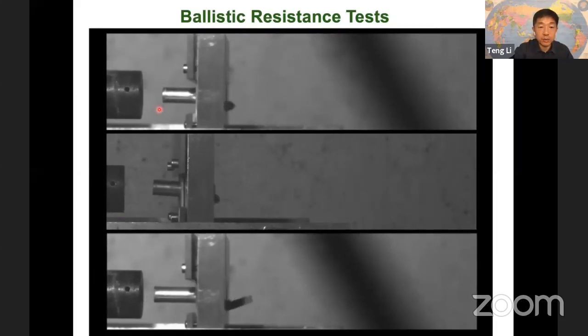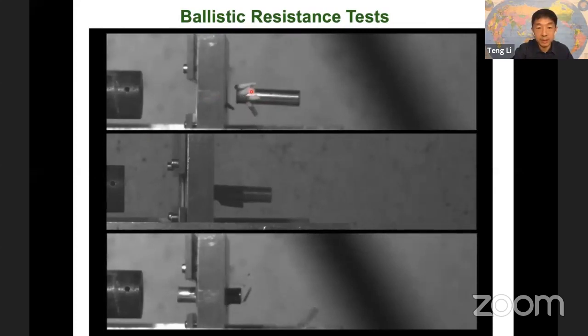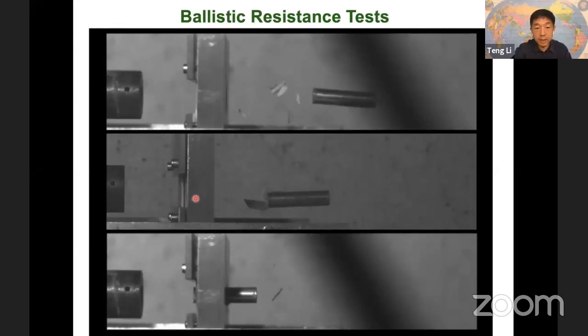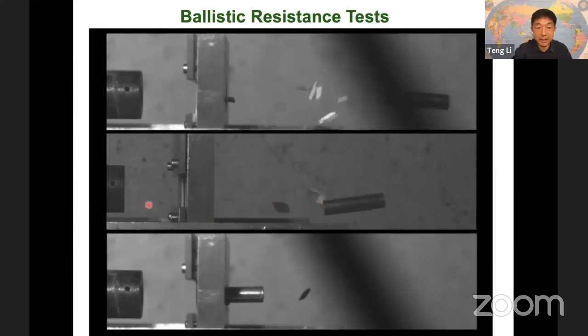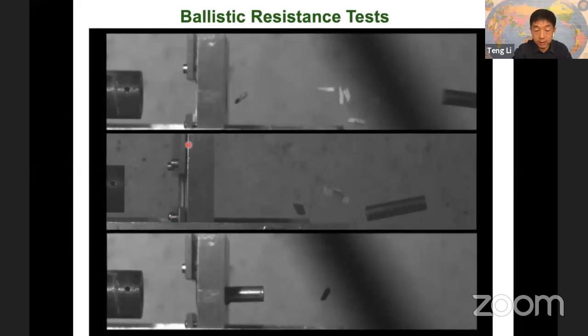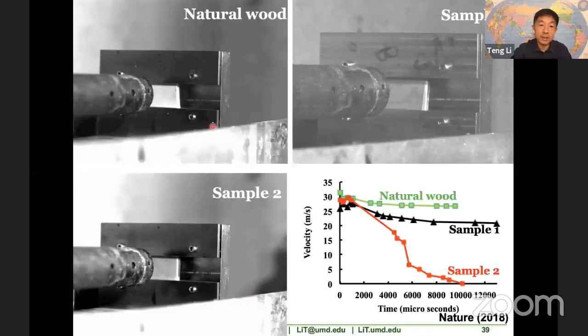As you can see, for the natural wood one, it can easily penetrate through, breaking the piece of wood, as you can see here. And the monolayer of this super wood can also be penetrated, but you can see that the velocity is lower, which means that this super wood absorbs more energy than the natural wood. And if you have this 5-layer laminate, it can completely absorb the kinetic energy of the bullet and actually trap the bullet here. So this is the Phantom camera video from the side.